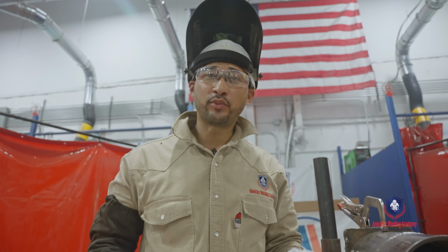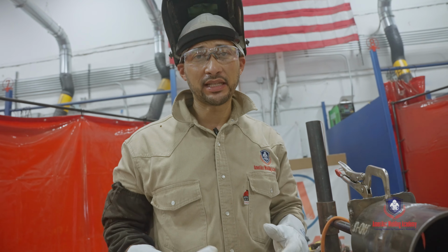There you have it, people. We are done with this from root to cap. Today we did a TIG root with 70S6 for our TIG root and hot pass. We used a nice heavy 5/32 gap. We used 7018 stick to fill and cap. This is our finished product.